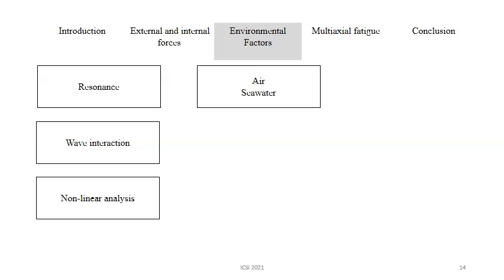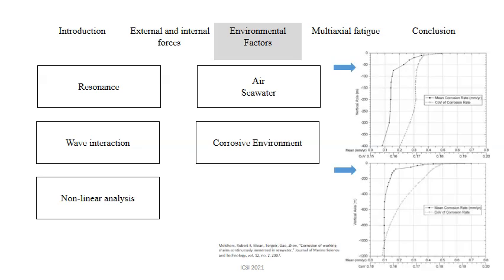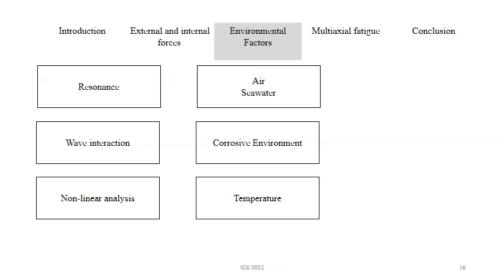The probabilistic models might be very beneficial for the prediction of marine growth. The probabilistic models of offshore structures are subject to corrosive environment and some factors such as temperature, dissolved oxygen, and water velocity can influence corrosion in these structures particularly up to 50 meter depth. In addition, increasing temperature can result in rising corrosion fatigue.